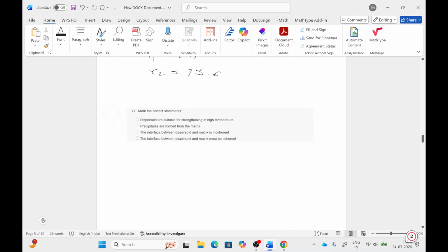Next question is to mark the correct statement. The first option says dispersoids are suitable for strengthening at high temperature—this is correct, since dispersoids are stable at high temperature. Second, precipitates are formed from the matrix: first we make the supersaturated solid solution, and after aging, precipitates form from the matrix—this is correct. Third option says the interface between dispersoids and matrix is incoherent—this is also correct, since the interface between dispersoid and matrix must be incoherent, not coherent. So A, B, and C are correct.